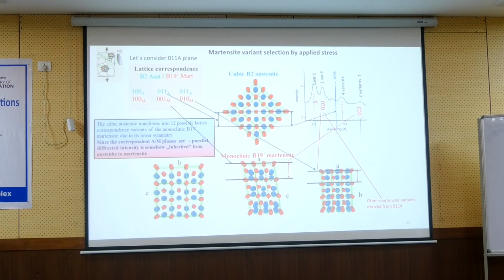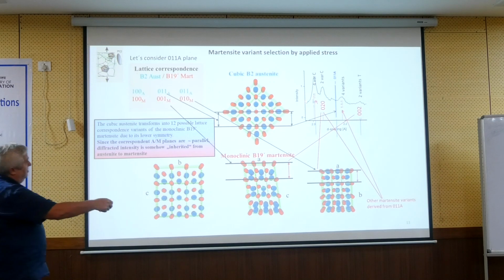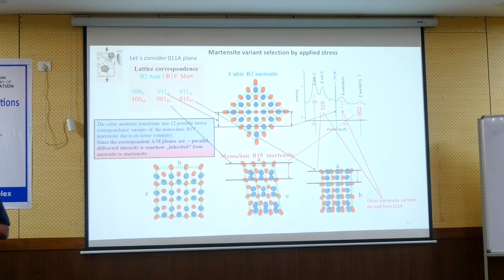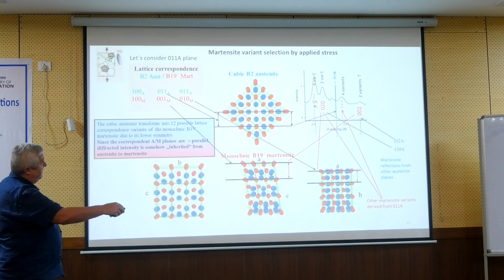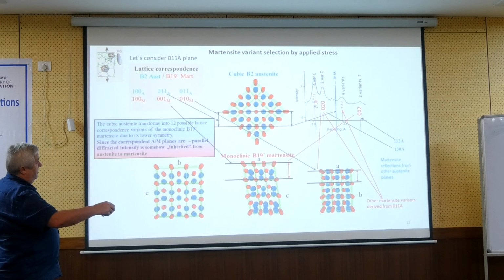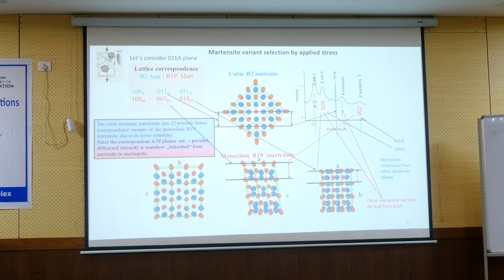In fact, there are two more because this 011 can, due to the lattice correspondence, go to four. It looks a little complicated, but now I have already associated 1, 2, 3, 4 peaks in this jungle, and I know from the crystallography that there are two more martensite peaks in this range. Now I have all the peaks here, and I can understand this kind of profile without any Rietveld analysis, just by considering the lattice correspondence between both phases. In the beginning we didn't understand it very much.